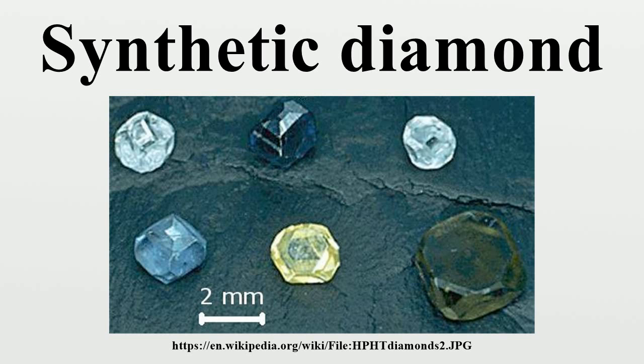The colorless stones produced strong fluorescence and phosphorescence under short-wavelength ultraviolet light, but were inert under long-wave UV. Among natural diamonds, only the rarer blue gems exhibit these properties. Unlike natural diamonds, all the GE stones showed strong yellow fluorescence under X-rays.